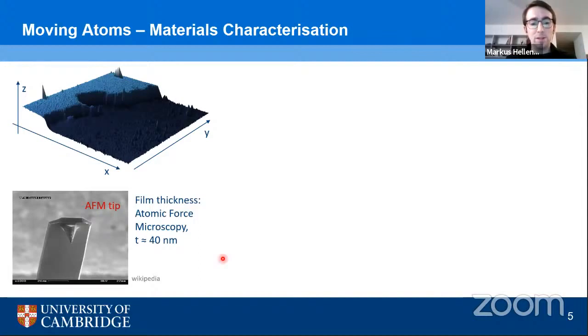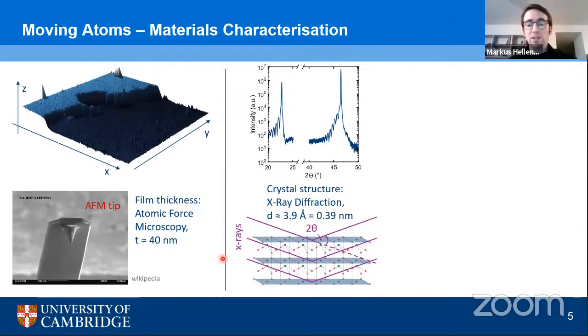As Professor Grosche just mentioned before, we can use X-ray diffraction to determine the crystal structure of our materials. So in this technique, we shoot X-rays at the material, and if it's crystalline, the order of the material will form planes which can diffract the X-rays, and by measuring the angle of the diffracted X-rays, we can then calculate the crystal structure that we have. So this would be an example for this. So we measure the intensity at different angles, and the peaks are in characteristic locations for different materials.